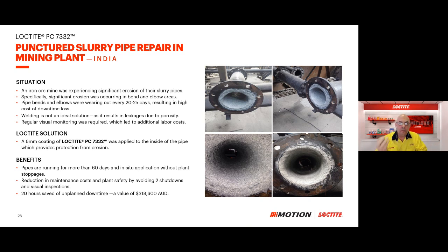So as you can see at the bottom there, 20 hours of saved unplanned downtime was a big factor, and that resulted in an overall saving of $318,600, which is not chicken feed. Okay, so that's a big saving. I think that this is one case history that actually proves that point significantly, where using a better quality, longer lasting wearing compound versus a competitor cheaper one, the labour savings alone are worth the extra little bit of cost.